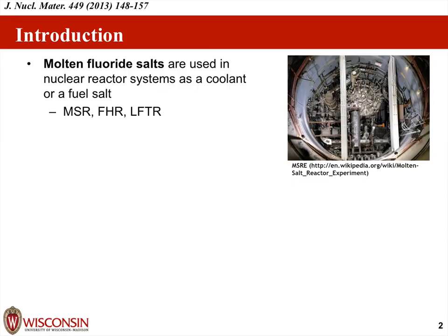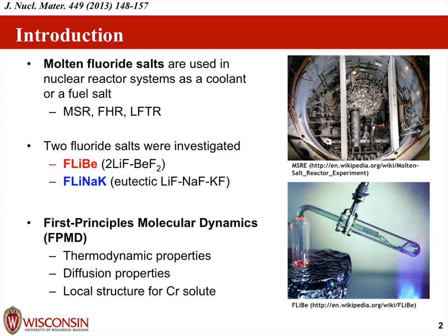We are interested in molten fluoride salts because they are being considered as a coolant for the next generation nuclear reactor systems. In this study, two representative fluoride salts for nuclear reactor systems, FLiBe, a contraction of its constituents fluoride, lithium, and beryllium, and FLiNaK, with its constituents fluoride, lithium, sodium, and potassium, were investigated by using first principles molecular dynamics, which is a well-suited simulation method for this kind of system. Thermodynamic properties, diffusion coefficients, and local structures for both pure molten fluoride salts and fluoride salt with dissolved chromium solute